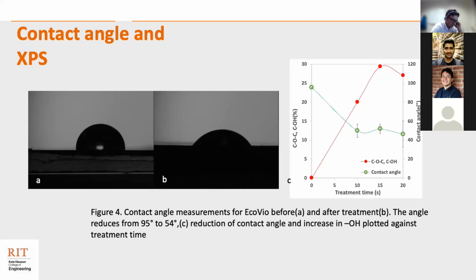On the other hand, the percentage of oxygen containing species on the surface, as measured by the XPS spectra that I'll talk about in the next slide, increases from 0% to 20% after 10 seconds of treatment, and goes up to 30% and 26% after 15 to 20 seconds of treatment.